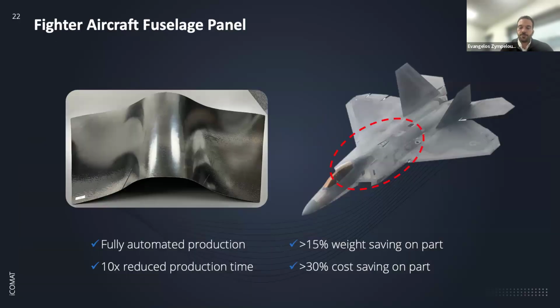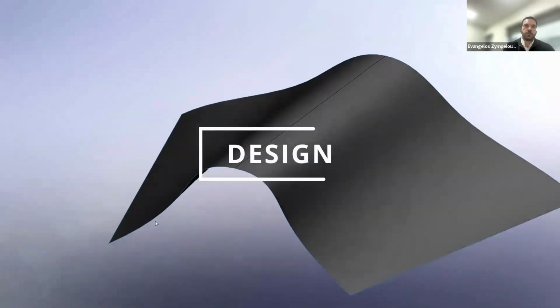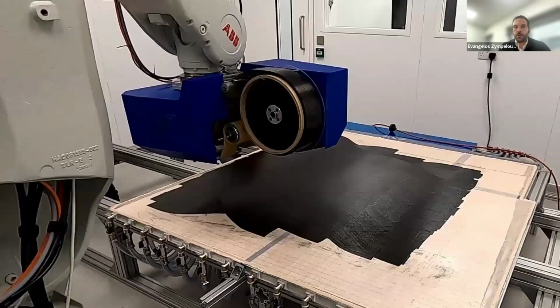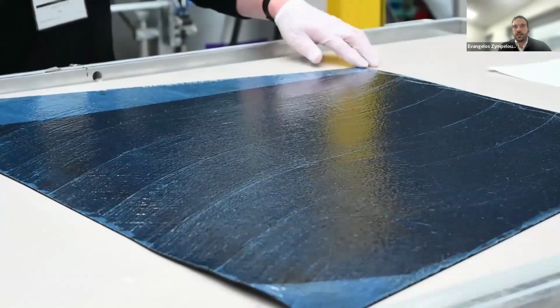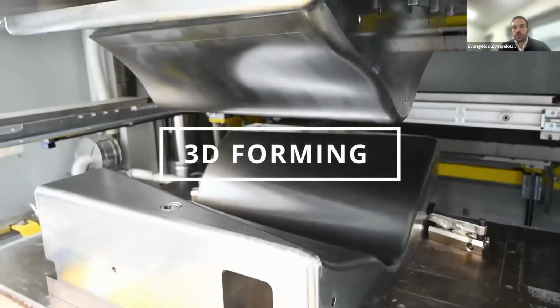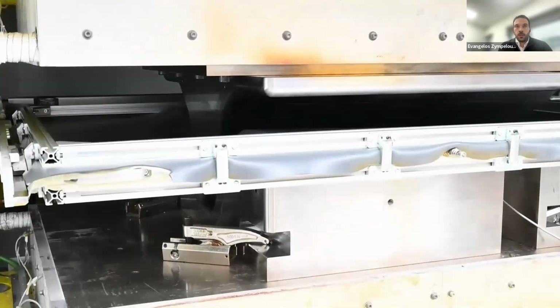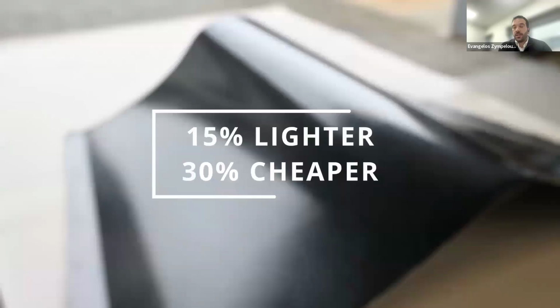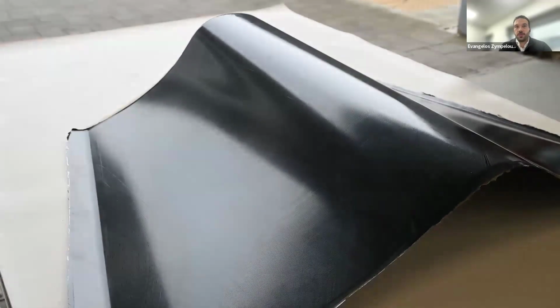Another quick example, this time is from the rear fuselage of a fighter jet. Same approach. We do the design, then we run a forming simulation, we do the flat stack, and in this case, we use a stamping system. So this is a heated press, so you cure while you press at the same time, and really it's beautiful. It's lighter, it's cheaper, and we literally made this 10 times faster compared to the nearest technology.